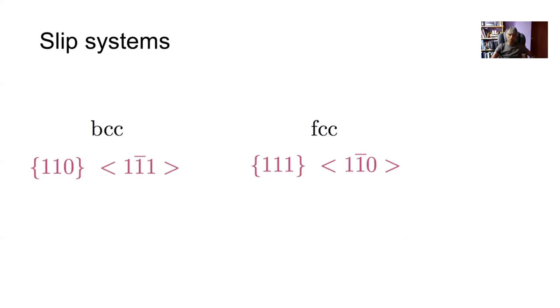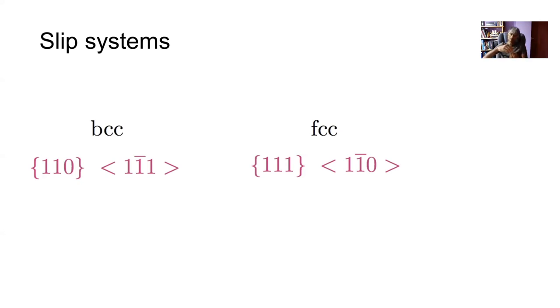Common metals are body-centered cubic and face-centered cubic, and they have slip systems that are easy to remember — a close-packed plane and a close-packed direction within that plane. There will be 24 variants of each slip system in each crystal. We can work out which particular slip system — for example, (1̄11) and [110] in BCC — operates by computing the Schmid factors for all 24 possibilities and finding the maximum.